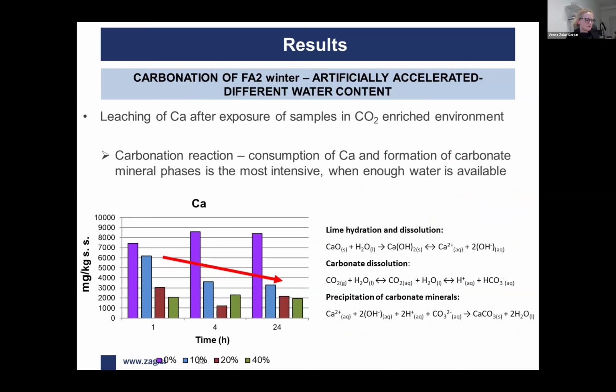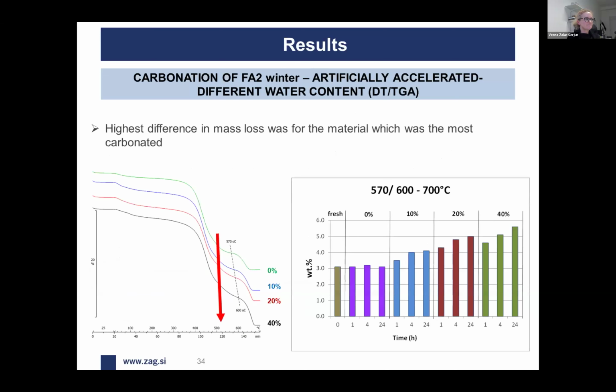The concentrations of calcium showed the opposite results than the silicon, but this is of course connected with the carbonation reaction. Less calcium in the 40% addition of water means a higher degree of carbonation. Probably some calcium also accounted for the mineralization of hydration products, but this trend is very obvious. The results further confirmed the highest quantity of carbonates, calcium carbonate, present in the sample with the highest water content.